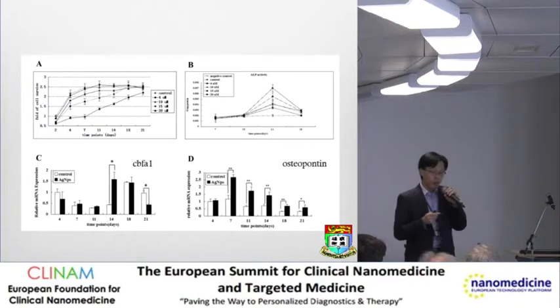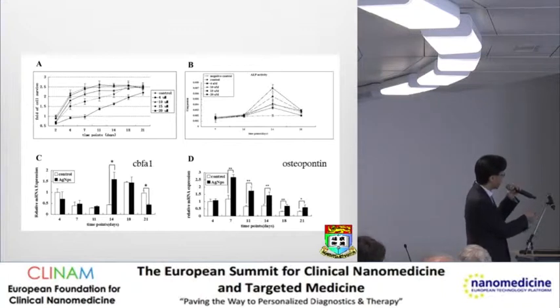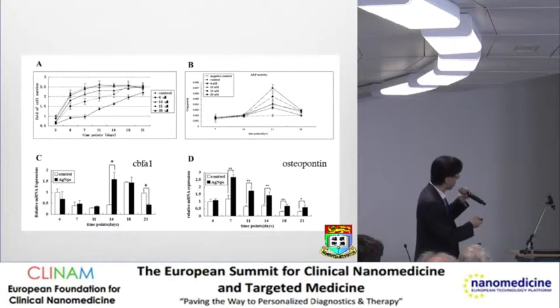We also looked at bone markers. If you look at alkaline phosphatase production from stem cells using silver, there is a large increase in production of alkaline phosphatase in a dose-dependent manner. Also, in terms of different bone gene markers, CBFA1 and osteopontin also increase with the addition of silver.